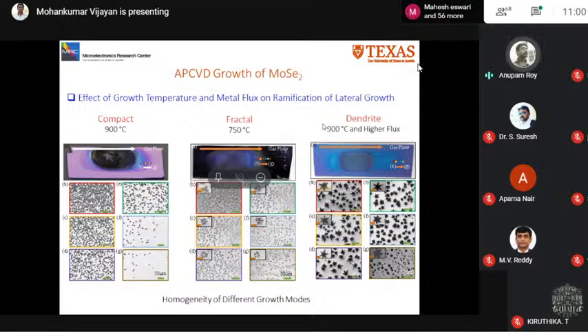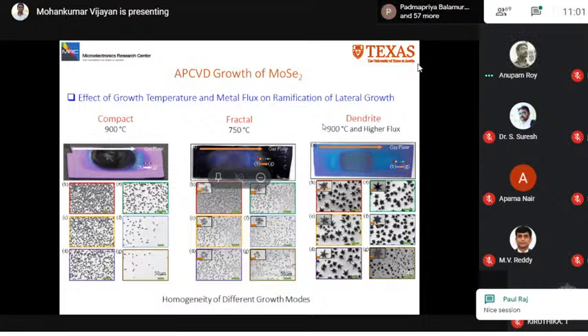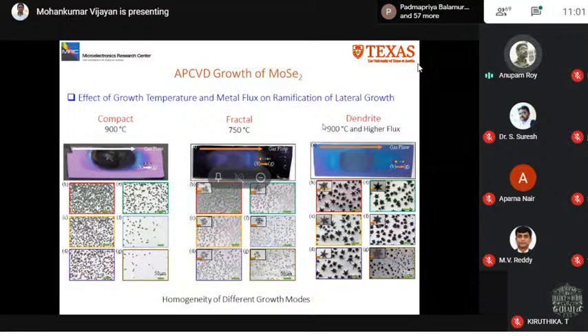The difference is the nucleation density, which is probably arising because as we move away from the center zone, the flux will be different if we move from B to G point. So you can see that the number of islands per unit area is not the same, and it is decreasing as we move from B to G. That is because of the flux. But it shows that the growth is very much reproducible and homogeneous, and it can produce the specific growth morphology at a specific growth condition.